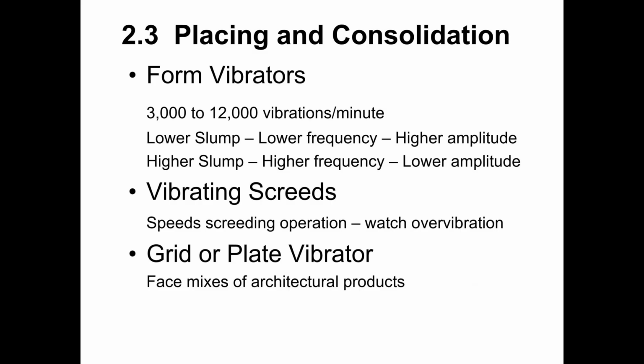Right, vibrating screeds, these are great devices because you're accomplishing two things at the same time. You're striking off the unformed surface of the concrete at the required elevation, and you're smoothing that surface, but you're also consolidating that surface. So with one operation, you're striking the concrete, you're smoothing it, and you're consolidating that surface. If it's a very thin element, such as a 2-inch flange on a double T, then you need to be careful to not over vibrate that concrete. Such a thin section of concrete, you need to move the vibrating screed along pretty quickly, or you'll cause segregation in that flange.